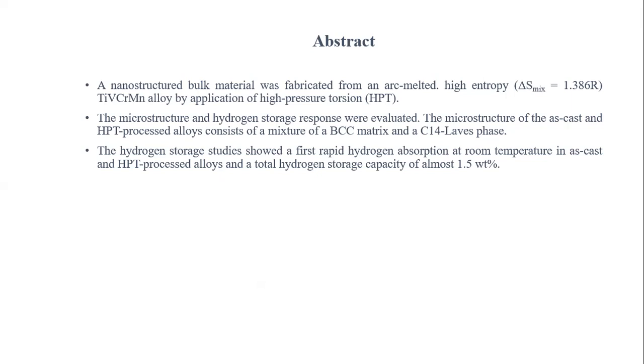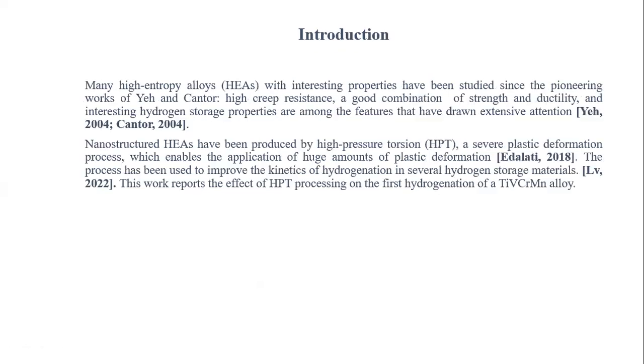The hydrogen storage studies showed a first rapid hydrogenation absorption at room temperature in as-cast and HPT processed alloys, and a total hydrogen storage capacity of almost 1.5%.